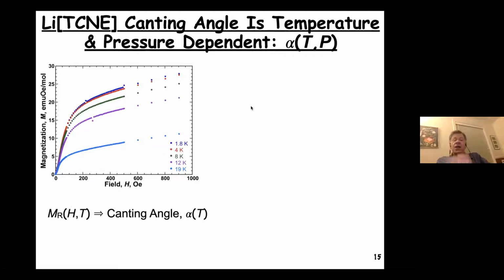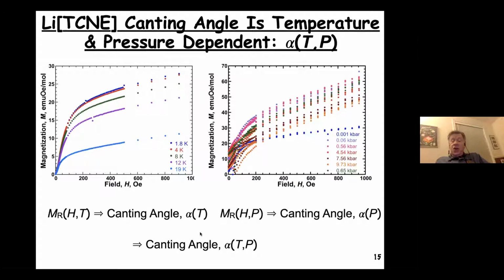Now, we can also look at the canting angle. From looking at the remnant magnetization as a function of field and temperature, we could actually determine the canting angle as a function of temperature. We can likewise look at the remnant magnetization as a function of field and pressure and get the canting angle as a function of pressure. And so in fact, we can determine the canting angle alpha as a function of both temperature and pressure. And as far as I can determine, and people can tell me differently if they know examples, this is the first example in the literature where in fact we have a temperature and or pressure dependence of the canting angle for a weak ferromagnet.